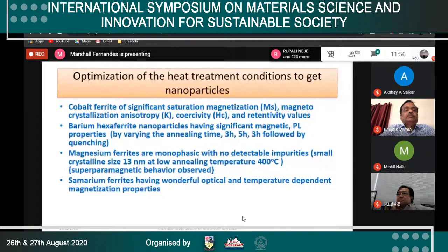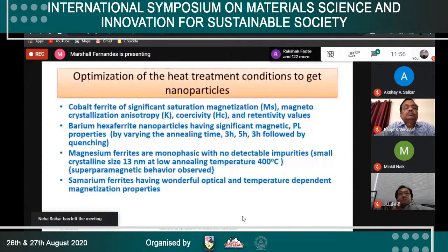Nanoparticles of different properties are prepared by varying annealing time. If we go for annealing for 3 hours, 5 hours, and then 3 hours heating followed by heat quenching, as I was telling, different particles have different properties. So different properties of the nanoparticles are there, and they can be used depending on the properties that we have.